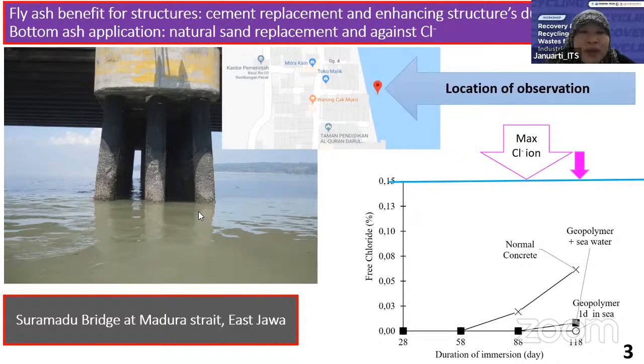And we put our specimens very near here. We put our specimen, our geopolymer concrete. Of course, this pile was made from conventional concrete, but we put our geopolymer specimens very near to the piles. And this is the location, and ITS is around here. And here is the result. This is the maximum free chloride ion standard. We have an Indonesian national standard to control how much free chloride ion can be found in the concrete. And this is the maximum.